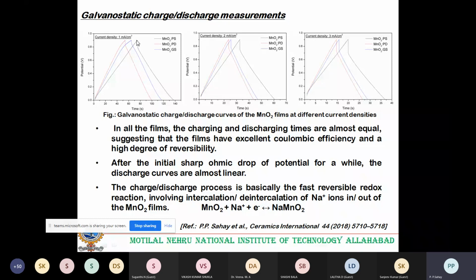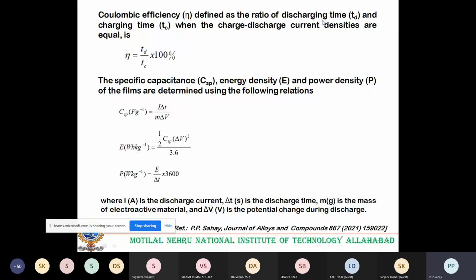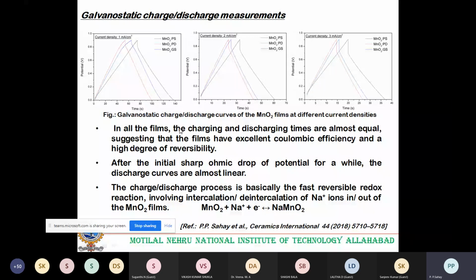So what does it suggest? It suggests that the films have excellent Coulombic efficiency and a high degree of reversibility. Okay, because there is a formula for the Coulombic efficiency, might be in the next slide. That is the Coulombic efficiency defined as the ratio of the discharging time t_D and the charging time, when the charge and discharge current densities are equal. So this is the normal formula. So this is the first inference which we have drawn.